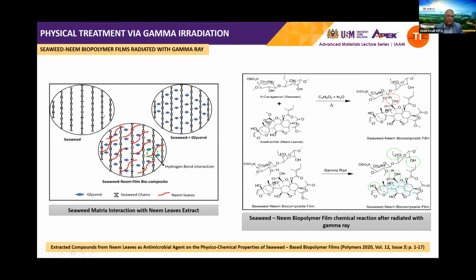In this study, seaweed was incorporated with neem leaf extract by inducing gamma irradiation for post-curing treatment. A simplified illustration of seaweed matrix interaction with neem leaf after casting is presented in the first figure, while the second figure shows the possible chemical interactions of gamma radiation on the seaweed neem film. The enhancement of the biofilm is induced through gamma radiation, forming stronger intermolecular bonds between seaweed and neem, thus increasing its properties. This finding was reported and published in Polymers journal in 2020.